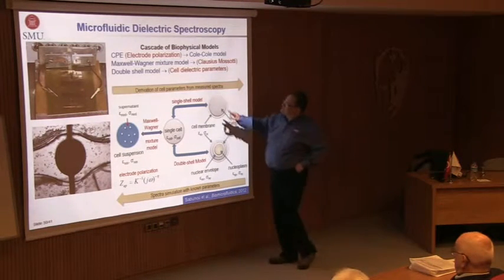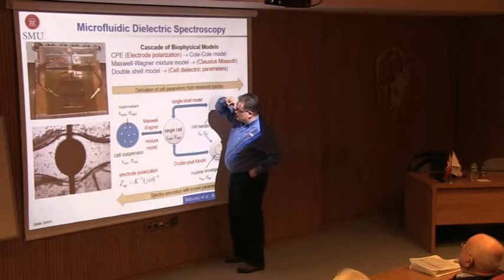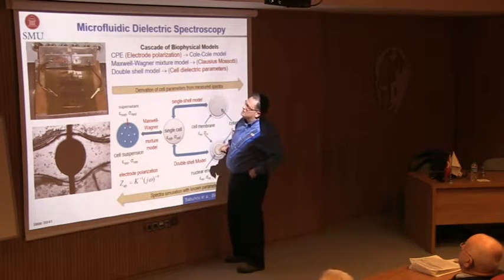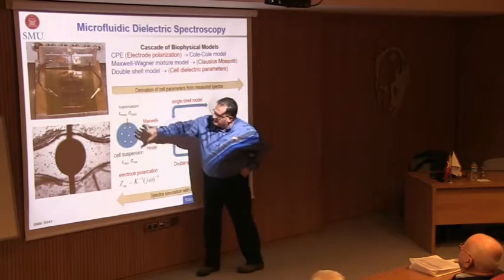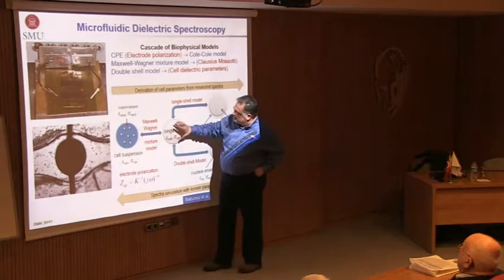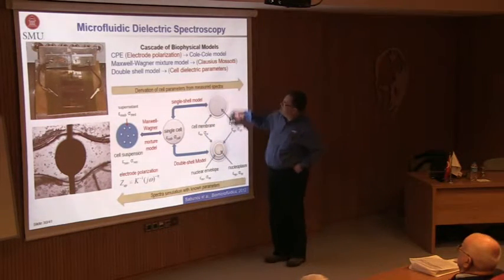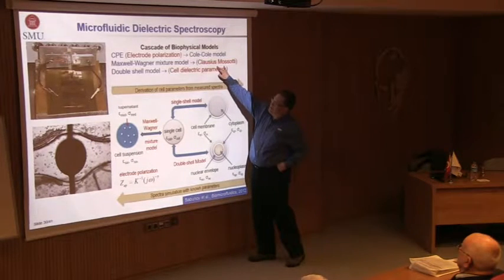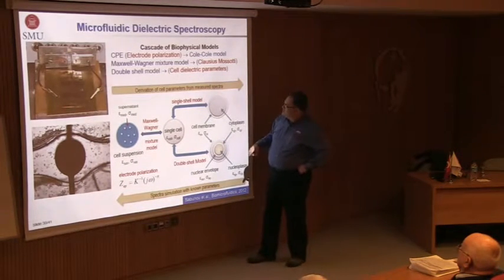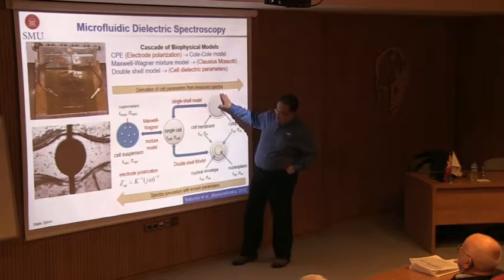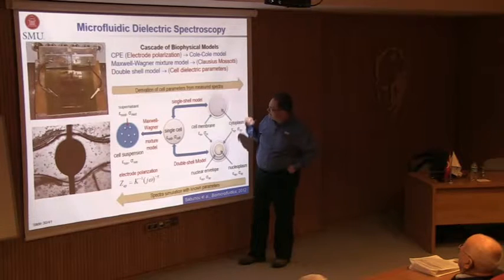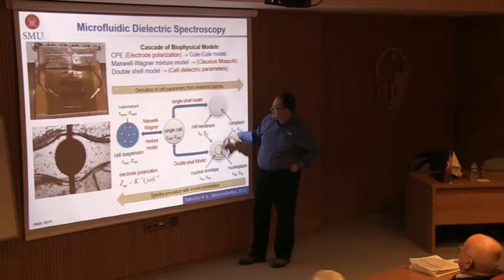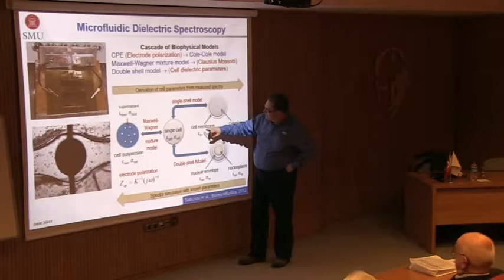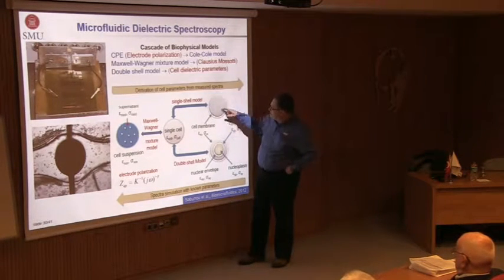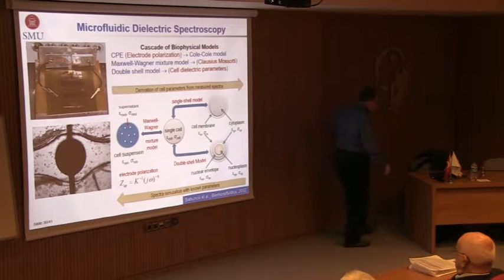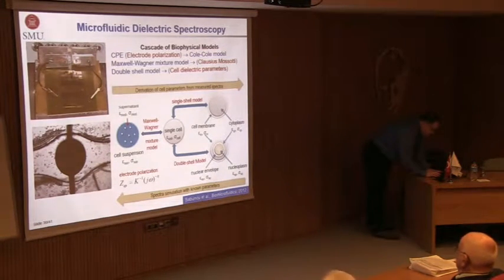I'm able to basically use the so-called Cole model that shows the dispersion for biological cells. Then using a mixture model, this is the mixture, I can actually obtain the properties for cells, which enables me to predict the Clausius-Mossotti factor. And even further on, if I assume that every cell is as simple as a single shell or a double shell, I can actually then extract the cell properties, like the conductivity and permittivity of the cell medium and cytoplasm and so on. And this can indeed create what I call quantitative biology.